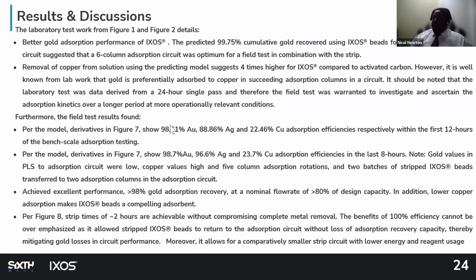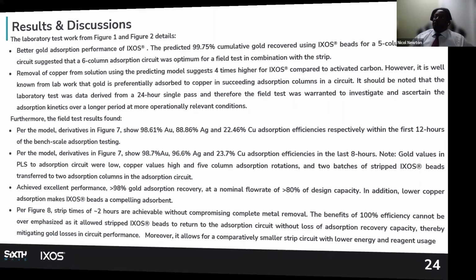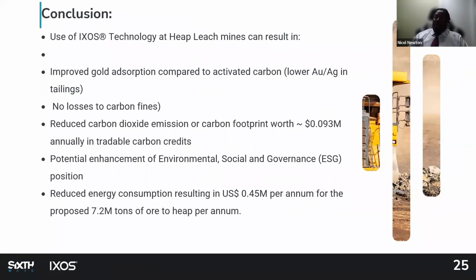And this information actually suggested the good performance of the IXOS bead, which is one of the unique characteristics of the beads itself. So in conclusion, the use of IXOS technology at heap leach mines can result in improved gold absorption compared to activated carbon, lower gold and silver in tailings, no losses to carbon fines, reduced carbon dioxide emission or carbon footprint worth approximately 0.093 million annually in tradable carbon credits for the 7.2 million tons of ore that was treated. This is a potential enhancement of environmental, social, and governance. We also realize that there will definitely be a reduced energy consumption, resulting in US dollar 0.45 million per annum of savings.